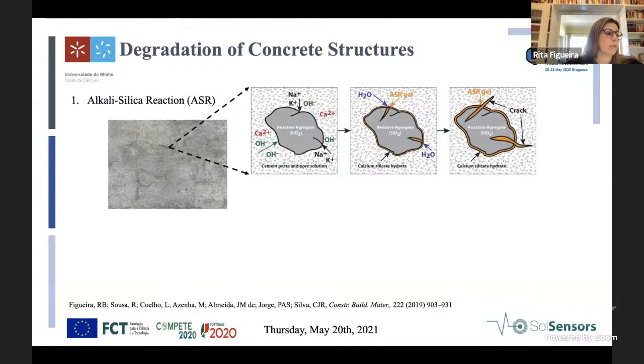The alkali-silica reaction only takes place in certain conditions. There are 4 main requirements that must be simultaneously satisfied. The existence of reactive aggregates with concentrations within a critical range, as the source of reactive silica; high alkalis concentration, or more precisely, high hydroxyl ions concentration in the interstitial concrete pore solution for silica attack. You also have to have a source of soluble calcium, such as portlandite, to react with the dissolved silica and form a deleterious gel. And finally, you need to have moisture.